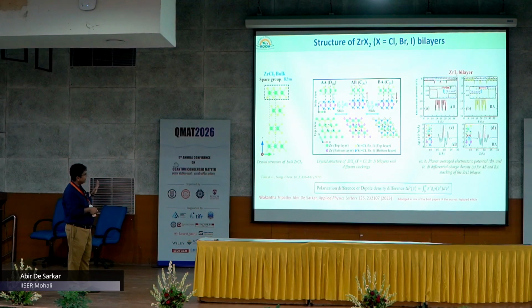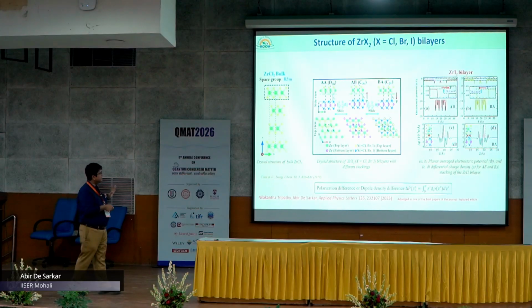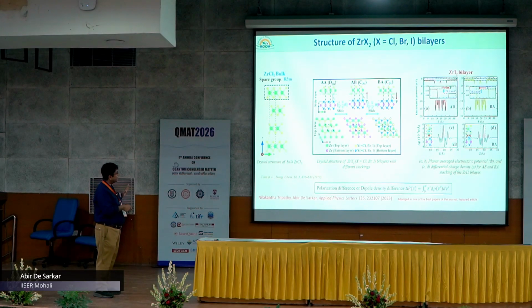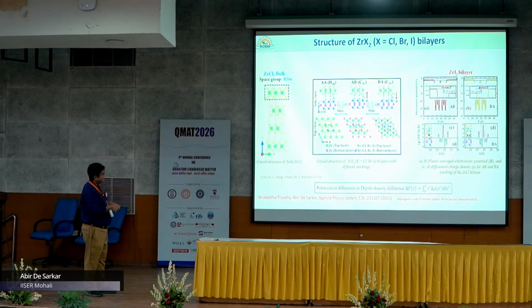In this AB stacking sequence, this is the difference in electrostatic potential, for which the polarization acts from this to this is the direction of polarization, and as you switch to the BA stacking sequence, the polarization reverses itself. So the relative electrostatic potential between the individual layers reverses itself. So that is the origin of this reversal in the polarization in this bilayer system.